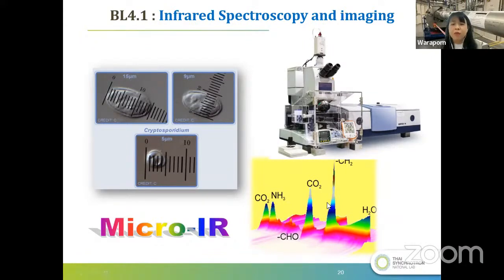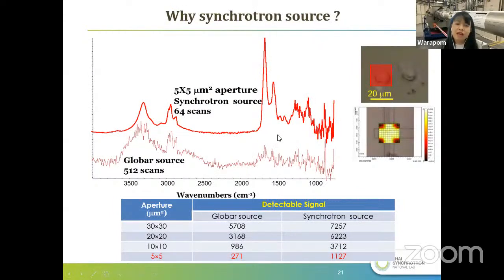You can get information on the functional groups like CO2, CHO, NH, C double bond, all like that. And if you use the synchrotron, you can get a very nice spectrum shape if you go down into an area of 5 by 5 micrometers square. But if you use a conventional FTIR microscope, the spectrum will be very noisy.